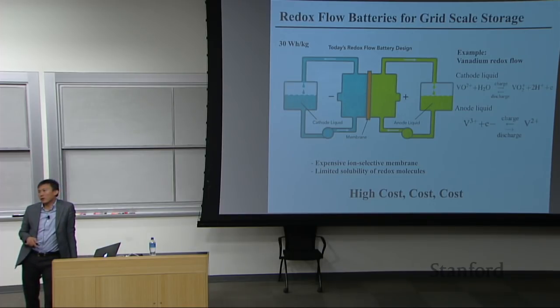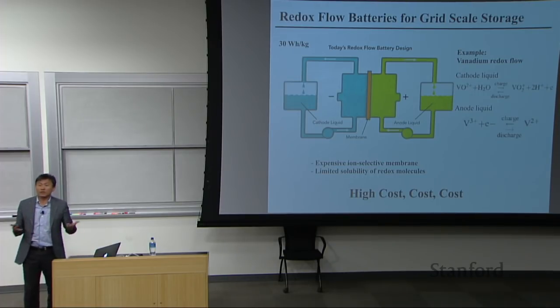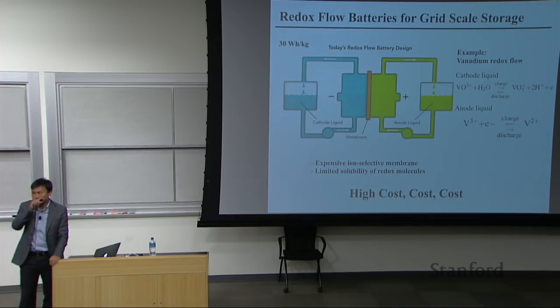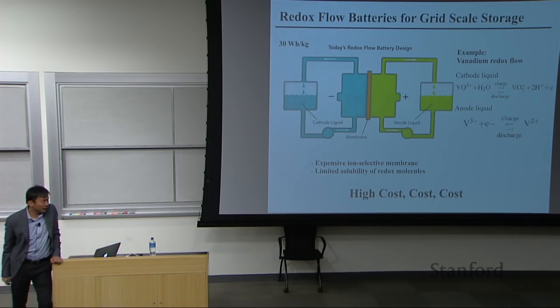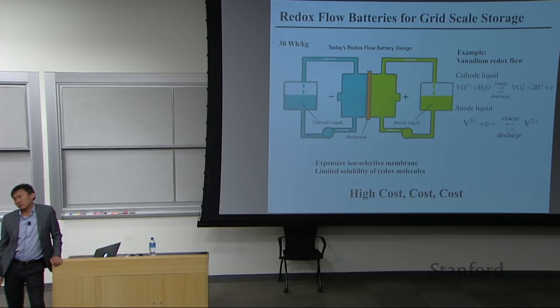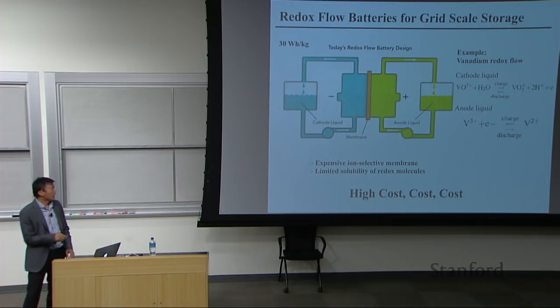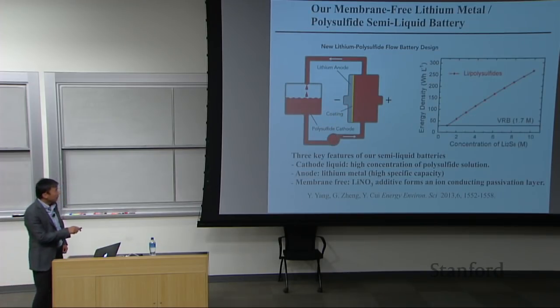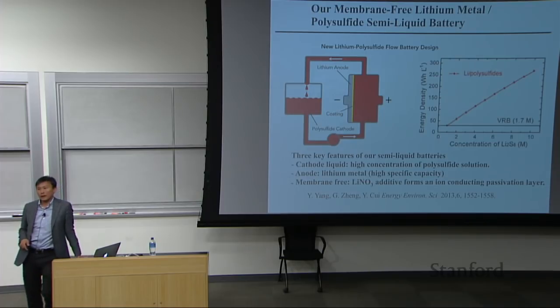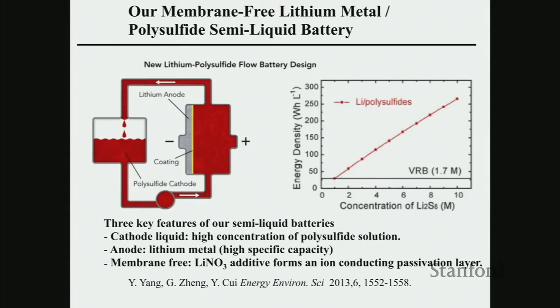For this redox molecule, solubility is not enough. You're talking about 30 watt hours per kilo. That's about 7 times lower than lithium ion. With all the controlling electronics going in, the system level cost, lithium ion now is about 250 dollars per kilowatt hour, 250. And a redox flow is about 400, 500 range. It's still too high. So if you could increase the energy you store, you can reduce the cost.